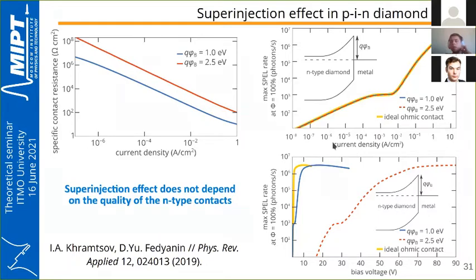The idea is that bad contacts result in higher voltages that should be applied. For example, for bad contacts with a Schottky barrier height of 2.5 electron volts, one should apply voltages above 80 volts. This is not suitable for on-chip technologies - we should deal with voltages near 5 volts or so.